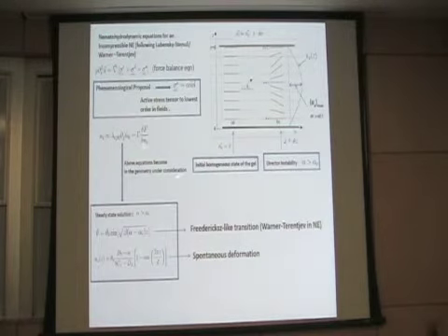To the lowest order in the field, since we are working in a linear theory, this is the most relevant term. So what we see is that, starting from a stable ground state, if one includes this term and solves the hydrodynamic equations, one sees a Freedericksz-like transition of the nematic field. Due to this distortion of the director field, there will be some spontaneous deformation of the elastomer. What I have shown here is the fundamental mode.